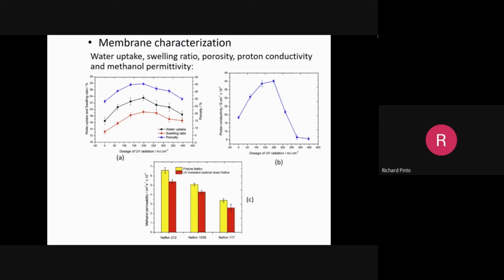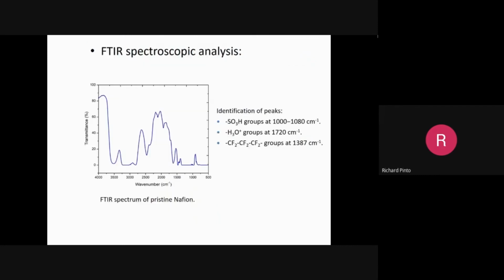Now what is the effect? Why does the conductivity increase? That is because of the optimization of the porosity through cross-linking. You optimize the porosity, with the result that you have better permeability of the hydrogen ions in the Nafion membrane. Okay. Now, why is this happening?